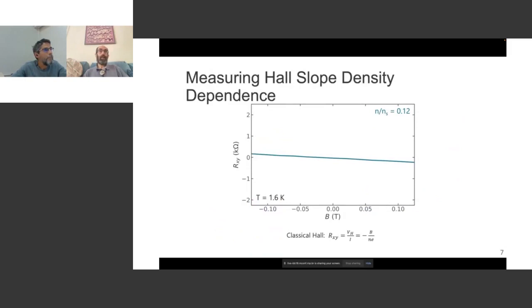So as you may know, if you put on a magnetic field and you drive a current, electrons get deflected by the field. They're deflected in one direction, and so you build up a voltage between the two sides of a sample, and so you can measure that Hall voltage. That's generally proportional to magnetic field at low fields. And it also allows you to extract the carrier density, because the fewer electrons there are, it turns out, the higher the Hall voltage. So here you can see the slope of the Hall effect as a function of magnetic field. These are low magnetic fields. This is a tenth of a Tesla. And you can see that there's a linear slope with magnetic field here.